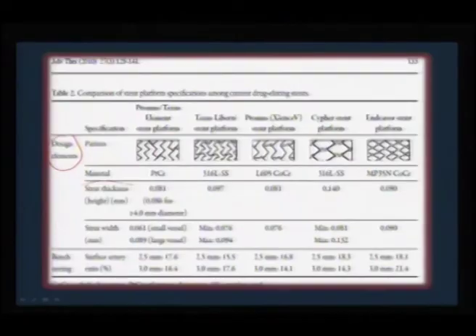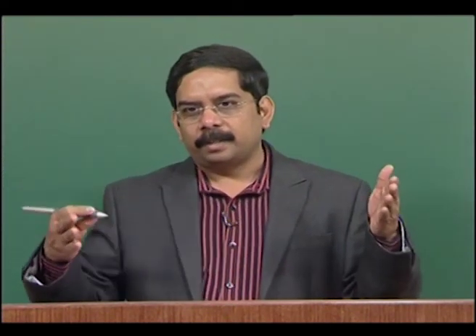One issue that is very important is the strut thickness. Strut thickness is nothing but the gauge. Usually when we talk about a wire, we talk about gauge. Gauge is nothing but the thickness. So for strut thickness, thinner is better, because if it is thicker, it is rubbing with the artery walls, and it is constantly in contact with your lumen flow. Therefore thinner is better, otherwise if it is thicker it is going to create more damage to the walls of your artery.